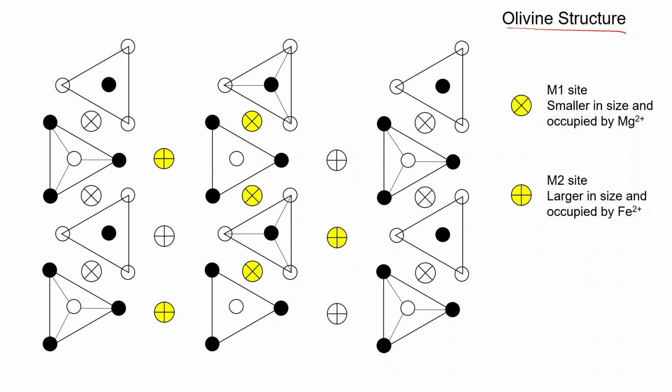In the very beginning, I said that olivine is a nesosilicate, which means that olivine has scattered or isolated silica tetrahedra. Olivine belongs to the orthorhombic system. So the structure of olivine consists of individual silicon-oxygen tetrahedra, which are linked by Mg-Fe atoms, each of which has 6 nearest oxygen neighbors.